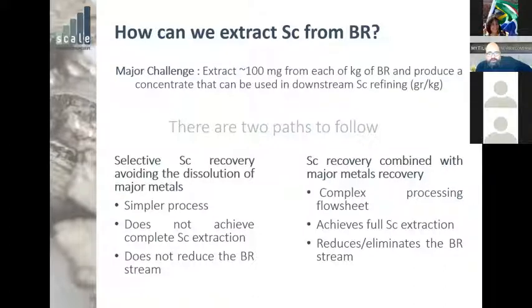Now there are two paths to follow. One is to try and selectively recover scandium, avoiding the dissolution of all the other major elements found in the bauxite residue. This makes for a simpler process, but it will not achieve complete scandium extraction, obviously. And at the same time, it will not help you reduce your bauxite residue in terms of waste prevention and waste handling, because you would only be leaching a very small portion of the residue. The other path would be to recover scandium along with the major metals. This would require a complex processing flow sheet, which could achieve full scandium extraction and reduce or eliminate the bauxite residue stream.